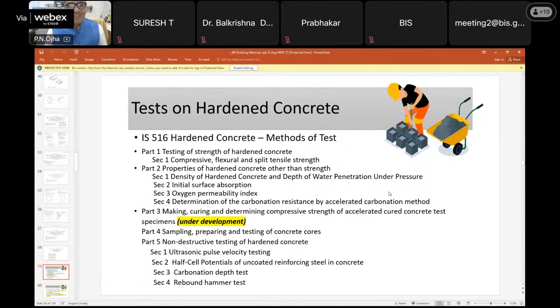Then part 3 explains the making, curing, and determining compressive strength of accelerated cured concrete test. So when we want a prediction of 28 days strength early, within 2-3 days, we have an accelerated test, and there is a method. This is under development right now. This standard is available for OPC only, and it is very, very old. So we are going to revise it. So this is also under development. I am also the convener for IS 516. So we are doing it in the committee. And how to sample, prepare, and test concrete cores. This is also available. And various non-destructive testing for evaluation of concrete structures.